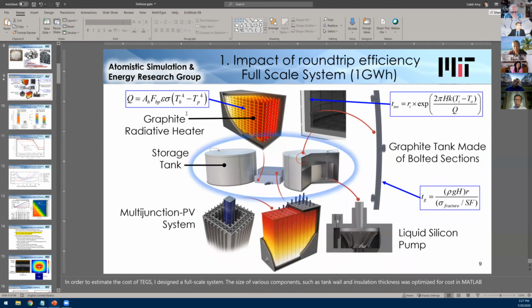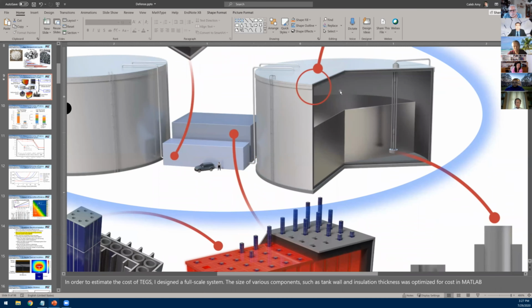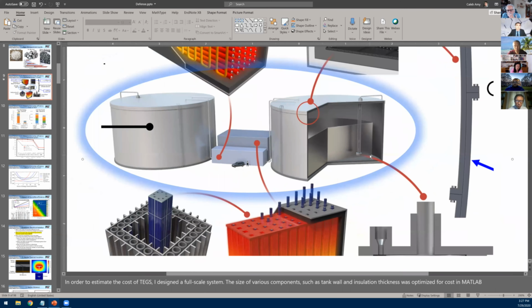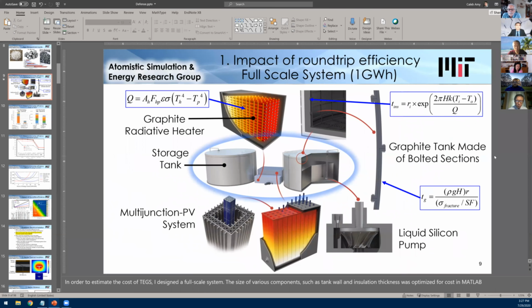When the pump is located in the middle of this tank, there's several meters of silicon around it. The thermal profile is really developed, so there would be maybe less than 1 Kelvin temperature difference throughout the pump. And so you wouldn't really get dissolution at the large scale. It's just because these experiments are smaller that we observe it in the pump.